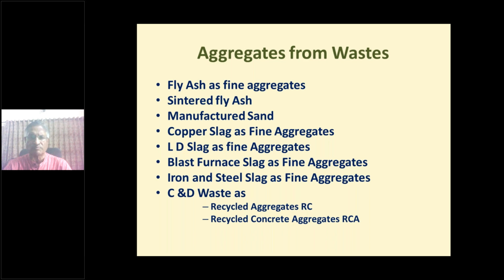Manufactured sand is permitted. Copper slag as fine aggregate is permitted in the code. LD slag as fine aggregate is permitted. Blast furnace slag as fine aggregate is permitted. Iron and steel aggregate as fine aggregate is permitted. Now C&D waste as recycled aggregate, RA or recycled concrete aggregate, both are permitted, but not to a full extent, but a certain percentage can be used.